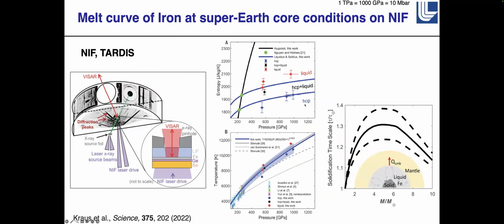Melt curves of iron under Earth core conditions. This was also Rick Krauss, who did an experiment similar to what he did in tantalum, but now at NIF, where we went to about 500 GPa and also about a terapascal. And we measured the transition from the HCP phase to liquid. We had one shot where we saw HCP plus a liquid, and then 3 shots where we saw complete liquid. And so we were able to extend the melt line of iron up to about a terapascal. This one shows entropy-pressure space, and this one temperature-pressure space.